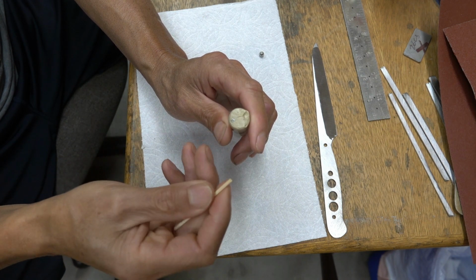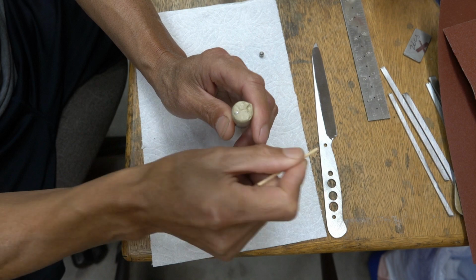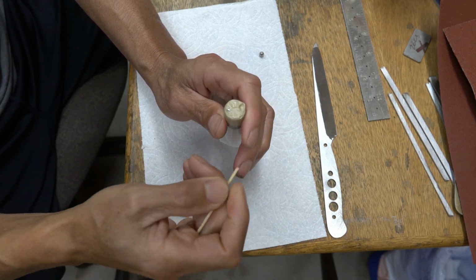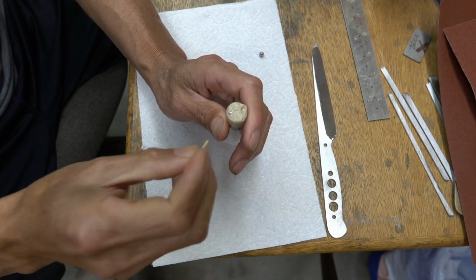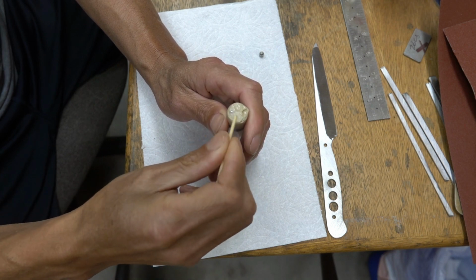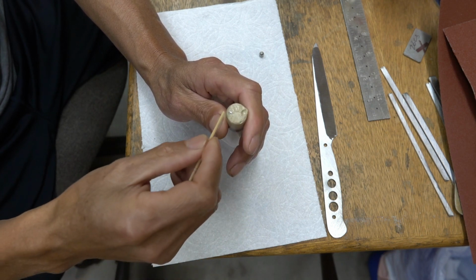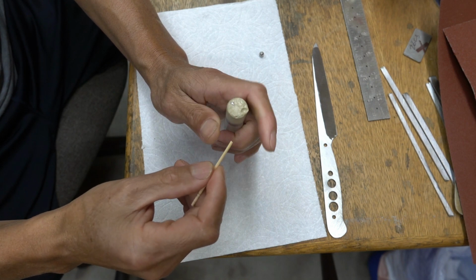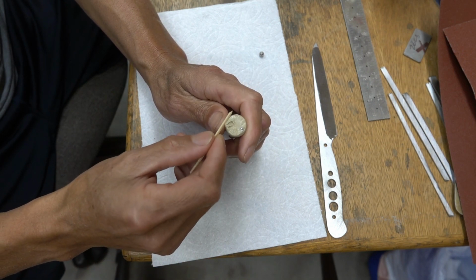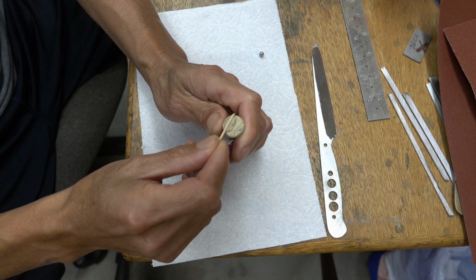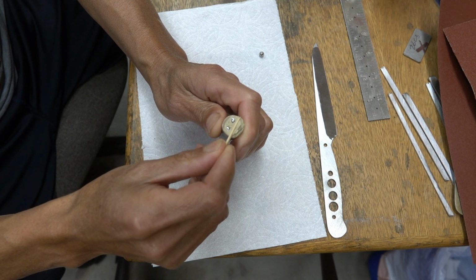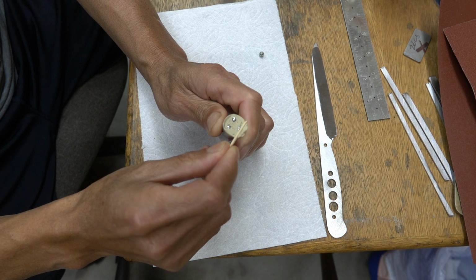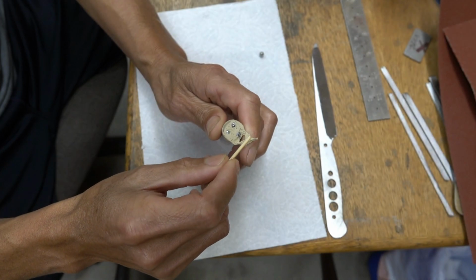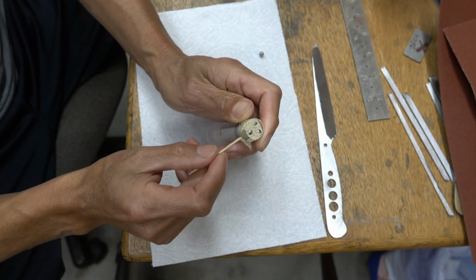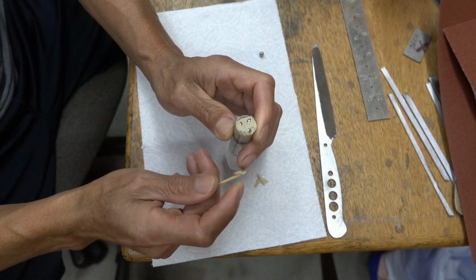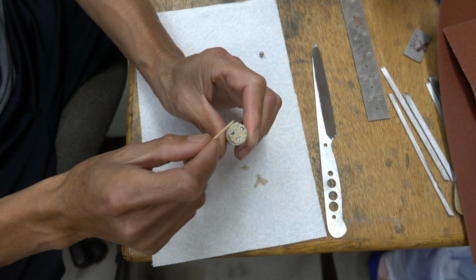And so now instead of a high PSI point that they can try to punch through, now you have a dull point. So you have a fixed dull abrasive plus a stumbling around abrasive that will cut into the matrix, right? So let's say that I'm going to cut through the matrix. Now after simulating, if I cut that much, I'm going to see some carbide protruding, right?